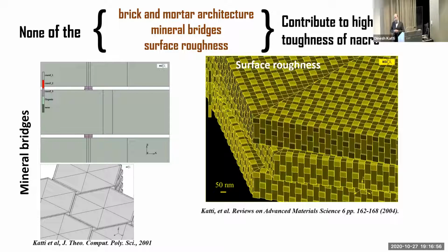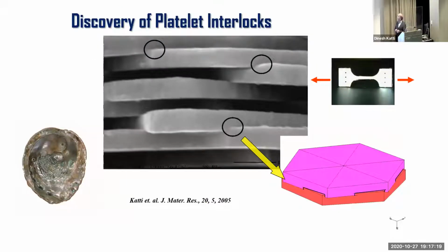But what we decided to do was to do our own experiments. We said, all right, let's do our own experiments, break the nacre, and look at the fracture surfaces. And then maybe that might give us a clue why the fracture toughness is so high. So our students meticulously carved out the nacre samples from the seashells. And then we pulled those apart and put those samples in a scanning electron microscope and looked at the microstructure. When the very first image came on the screen, we just jumped out of our seats.